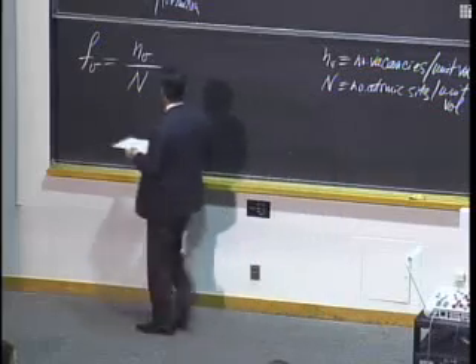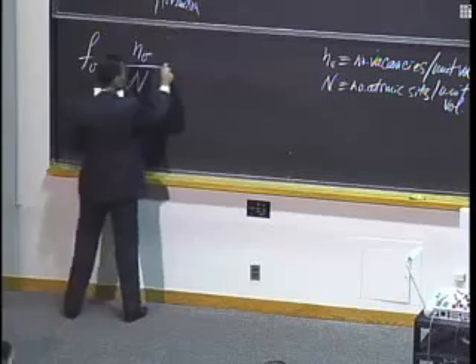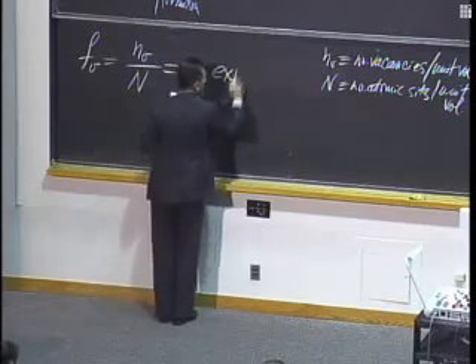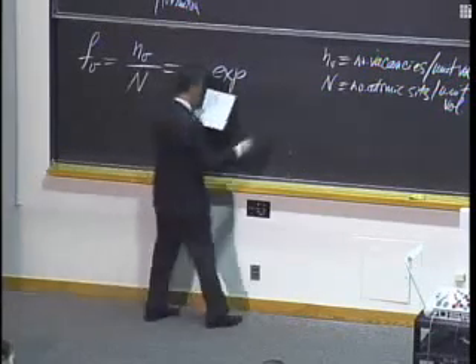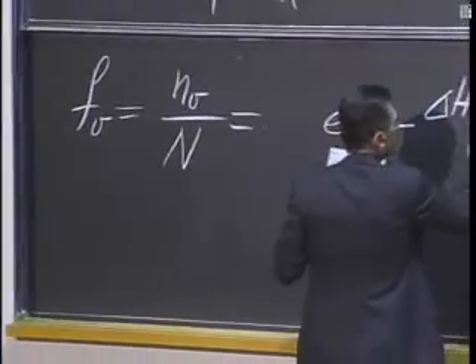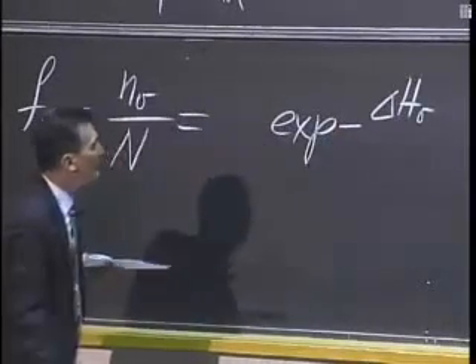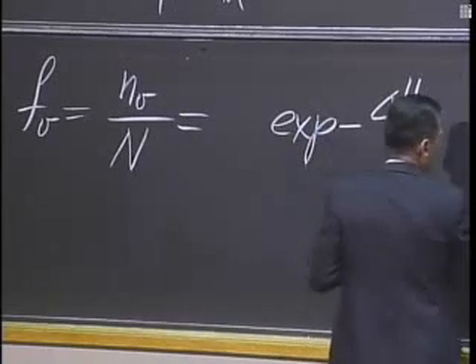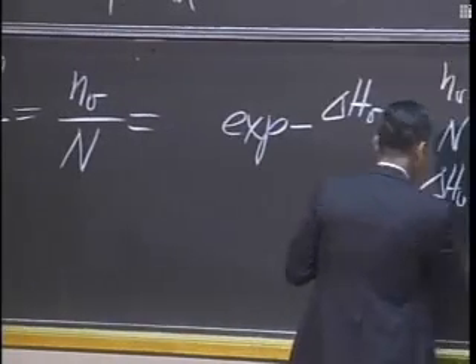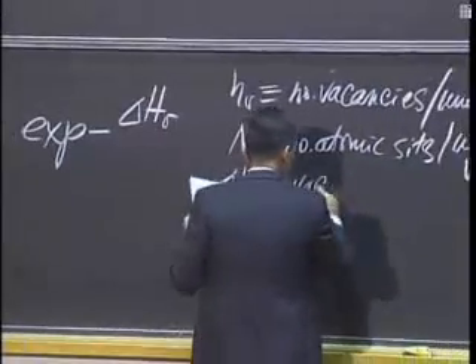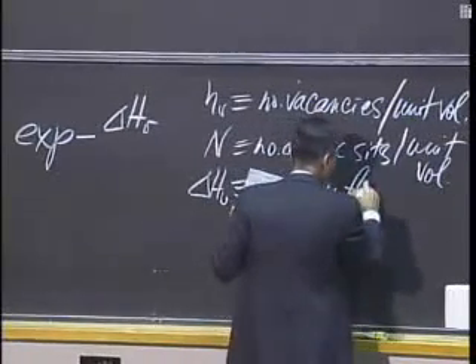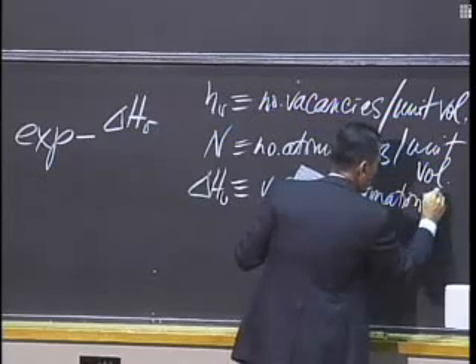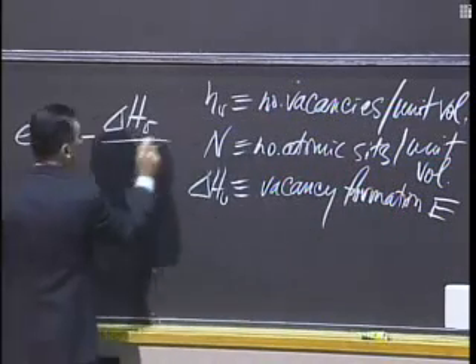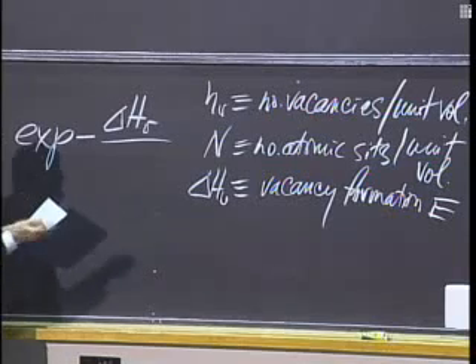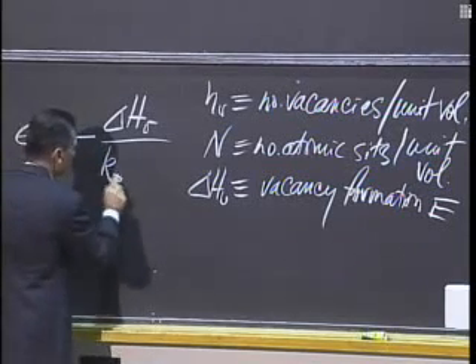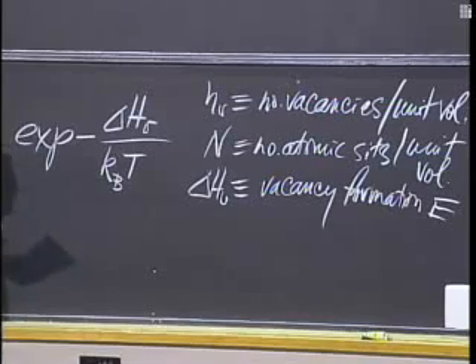Okay, and that's going to be given by the ratio mediated through this exponential of the energy, and I loosely move energy and enthalpy back and forth. This is the enthalpy of vacancy formation, the vacancy formation energy, over the thermal energy. And how do we get a rough measure of the thermal energy? Product of the Boltzmann constant and absolute temperature.